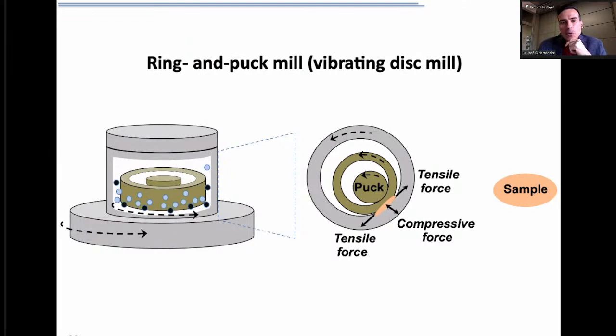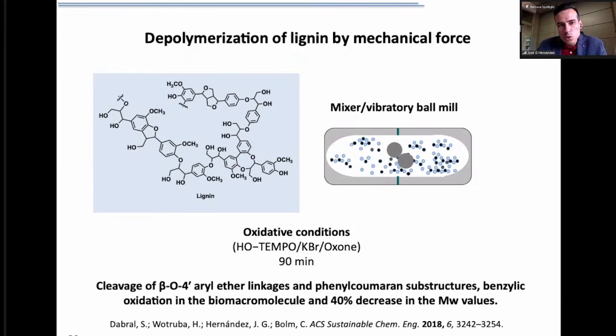In the past, we were working on trying to break down lignin. So we were interested at that moment in depolymerization of lignin, trying to work on the valorization of a biomass material. And we demonstrated that under certain conditions, it was possible to carry out the cleavage of lignin to access aromatics within the structure. The conditions were oxidative, in which we mixed together hydroxy-TEMPO, KBr and Oxone for 90 minutes within a ball mill, a mixer mill, let's call it. And the reaction proceeded quite well. We observed oxidation and cleavage, and we determined that after 90 minutes, we achieved a 40% decrease in the molecular weight of the lignin.